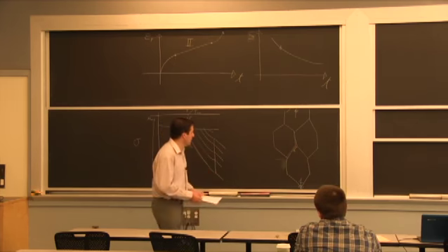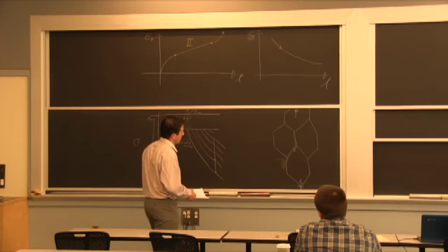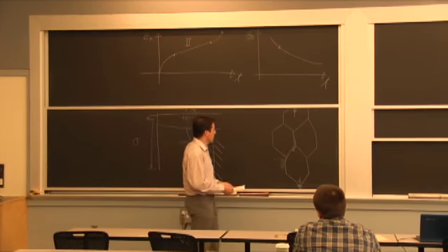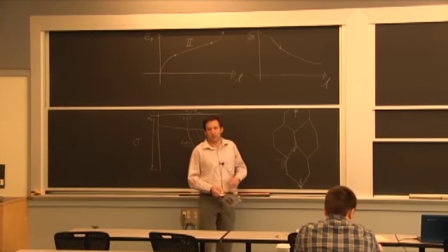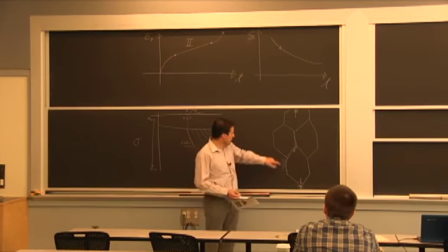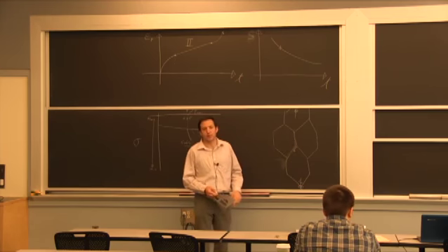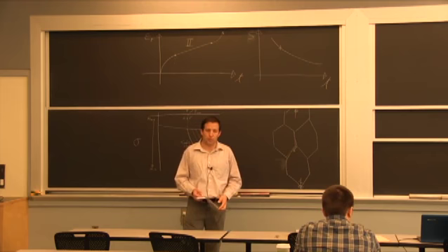You can already think that one way to reduce it is to make the grains bigger. If you make the grains bigger, you have a bigger average travel distance from this location to around here, and your creep rate's going down.